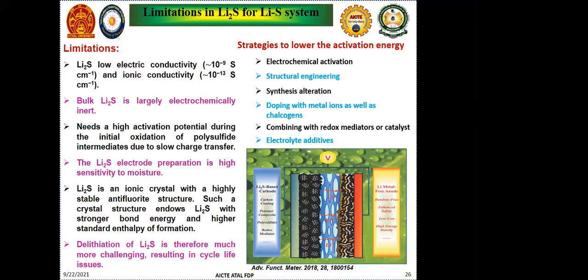In general, Li2S synthesis is done by ball milling, because it is very easy and we can get it moisture free. We can synthesize this in a moisture-free environment, like generating it in a glove box and then going for ball milling. And also the doping of different metals or chalcogens can help the Li2S. As I mentioned, it needs a high activation energy, so doping with other material will reduce its activation